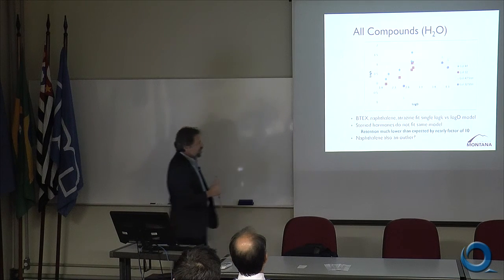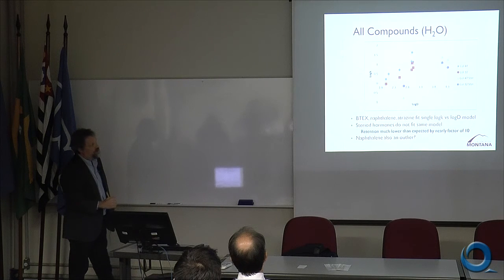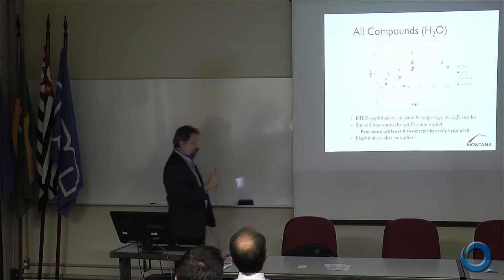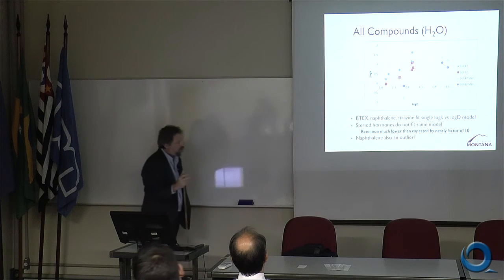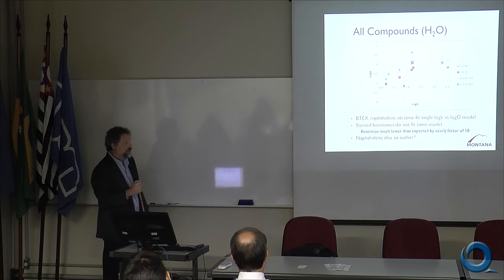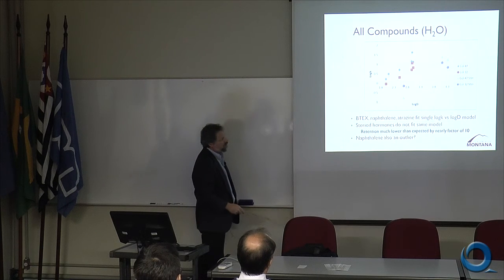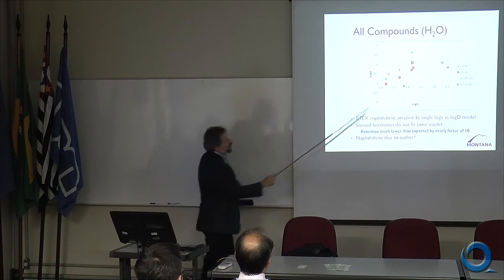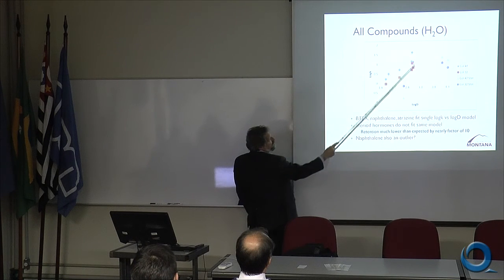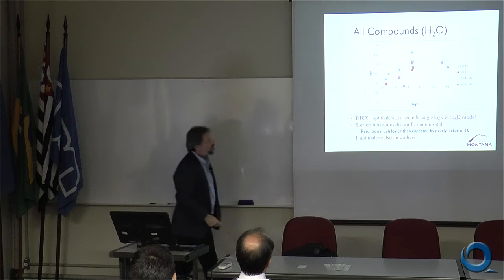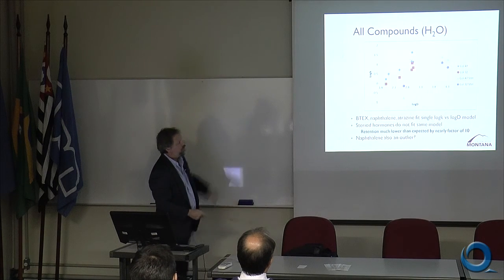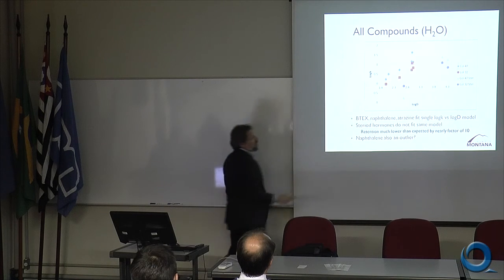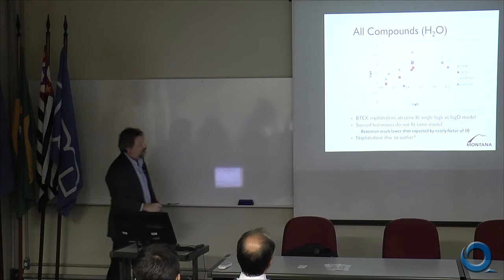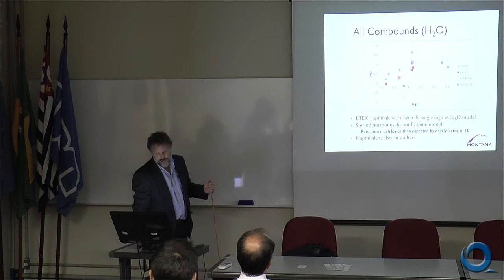It may be that this would be a nice feature of these nanoparticles, that they are selective for specific types of hydrophobic compounds and not very retentive toward other types of compounds, but we don't know yet exactly which compounds to expect would have high or low retention. The other thing to notice on this plot, naphthalene is this point right here for column 47 and this point right here for column 32, and it seems to be falling above the plot for the BTEX material. So it may also be an outlier. These PAHs may actually be showing stronger retention than what we would expect relative to the BTEX series.